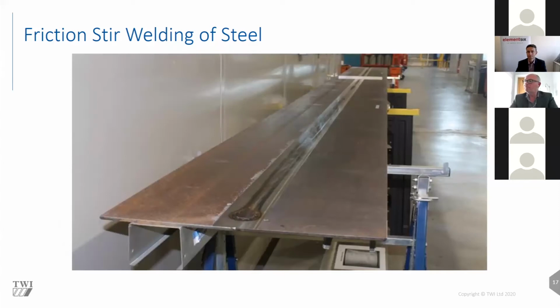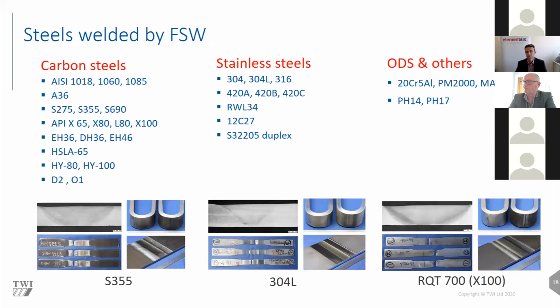What we see on the screen at the moment is just an example of a friction stir weld in 1/4 inch or 6 millimeter thick carbon steel plate. That's 6 meters long, and it just shows how little distortion we get along the length of that plate. From end to end, we saw just about 2 millimeters of distortion. So that's pretty good going. On the next slide, we'll see some of the steel grades that have been welded.